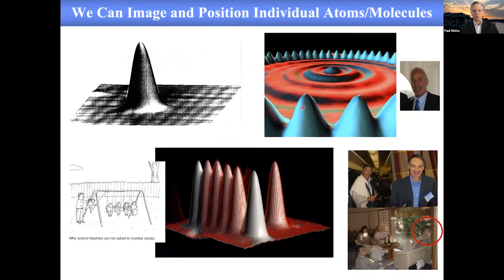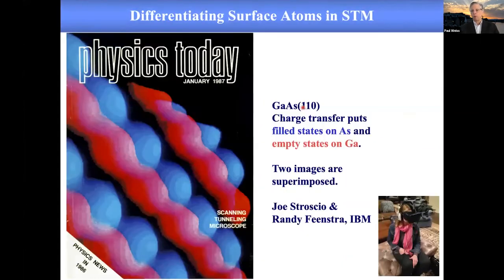and a number of other famous images. In addition, to me, the most important STM image ever recorded was this one out of the IBM Yorktown labs with Joe Stroscio and Randy Feenstra, showing that they could measure both the empty and the filled orbitals on a surface. In this case, the stoichiometric gallium arsenide 110 surface, where, because, sorry, I teach freshman chemistry, gallium is less electronegative and arsenic more, there's charge transfer from gallium to arsenic. So all the filled states sit on the arsenic and all the empty states sit on gallium.